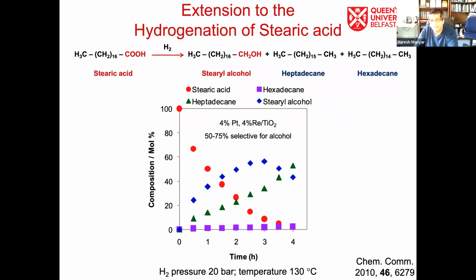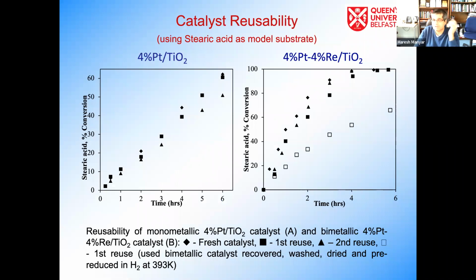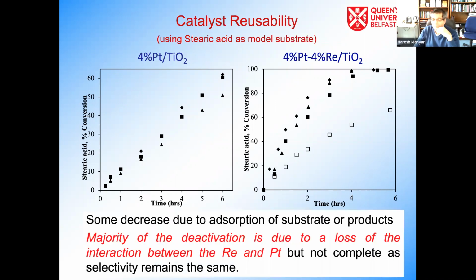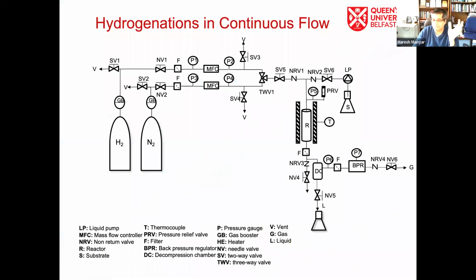So again, we studied stearic acid as a model substrate to understand more about the mechanism behind the reaction and kinetics behind the reaction so that we can design the reactors for that. And we studied the reusability of the catalyst, which was decent. However, when we recover the catalyst in the bimetallic materials, we have to wash it, dry it, calcine it, pre-reduce it, a number of steps here. However, whenever we do all these steps, there's always a possibility that we lose the interface between the bimetallic catalyst, which we don't want. And that's why traditional batch reactors are not really that efficient.